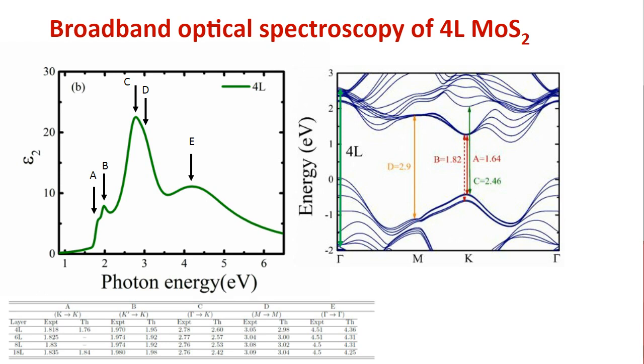You can see even at 4 eV, the dielectric constant is above 10. And the dielectric constant can go as high as 20, 25 for MoS2 around the C and the D exciton. So these are very, very strong light absorbing materials. Even for 4 layer, a single layer is very strong, like I was saying before, because of direct transitions. These are also other direct transition processes, and these are also very strong.